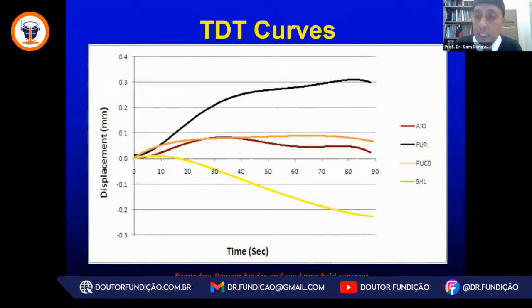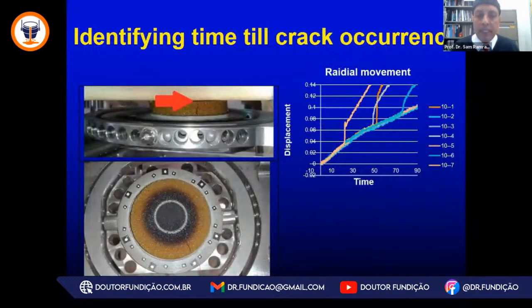We measure those changes. So certainly more stable sand systems can help to minimize the distortion problems. And that is the reason some of our foundries have adopted the ceramic sand media to go along with a suitable chemical binder system after qualification regimes and testing.